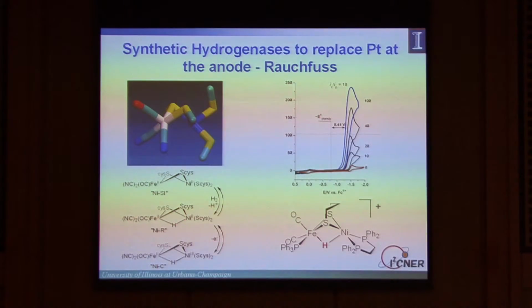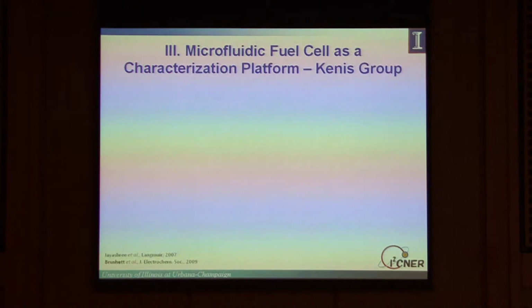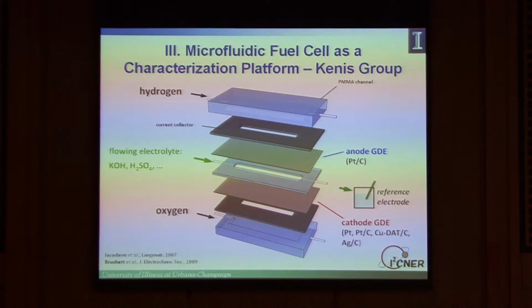At the same time, my colleague Tom Rauchfuss has been working on the anode reaction. Recall that's where you're oxidizing hydrogen. And he has a biomimetic catalyst based on these iron-nickel hydrogenases right here. So here is his catalyst, and he's shown that he can get a very efficient oxidation of hydrogen with only a small overpotential. In fact, the best overpotential for hydrogen on this material.